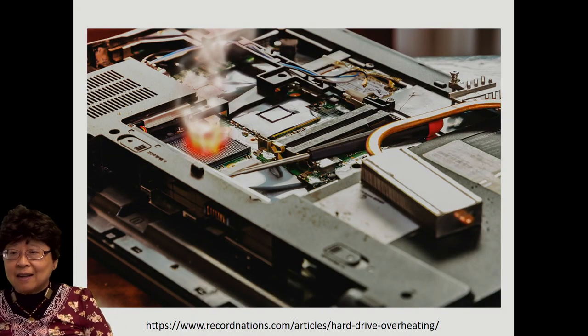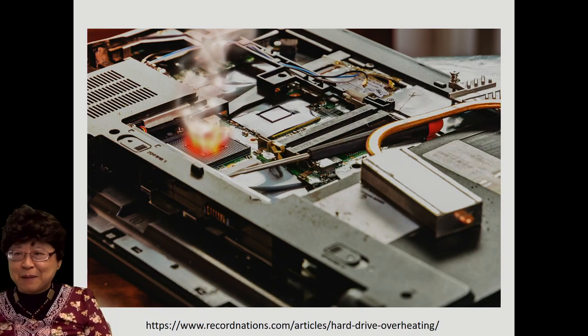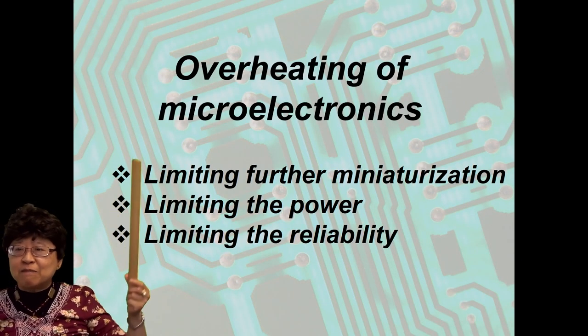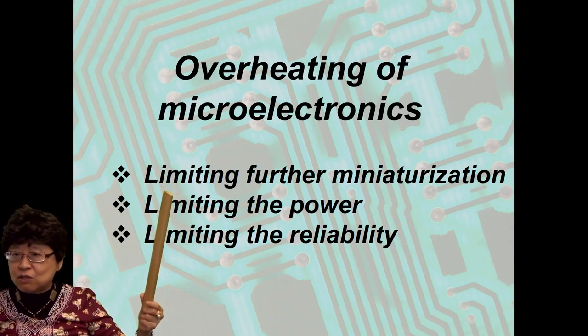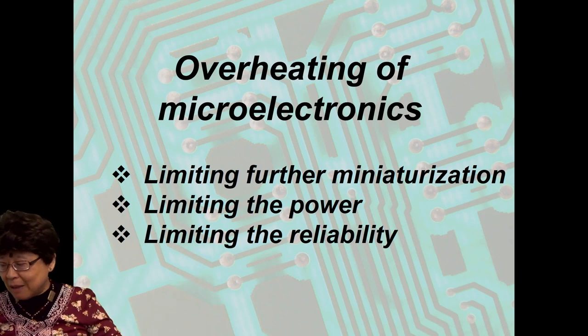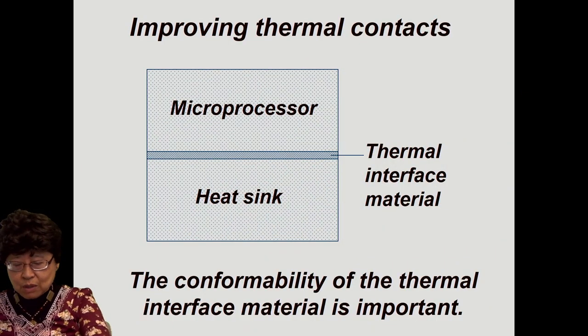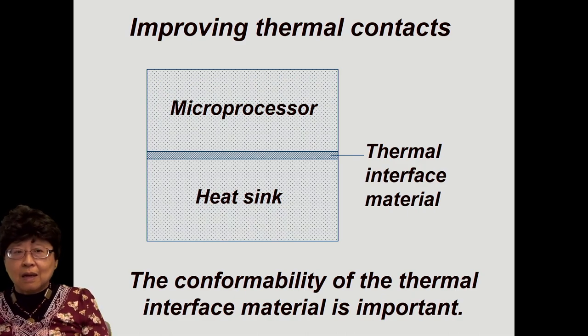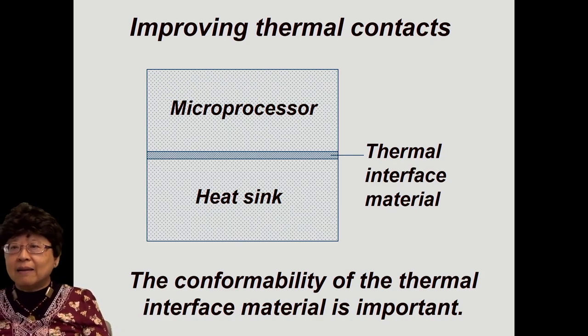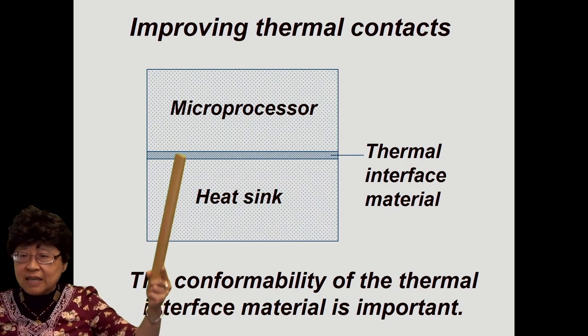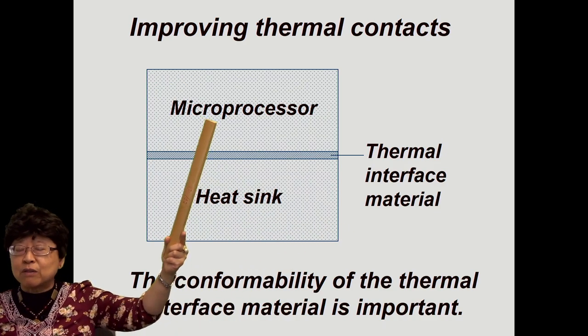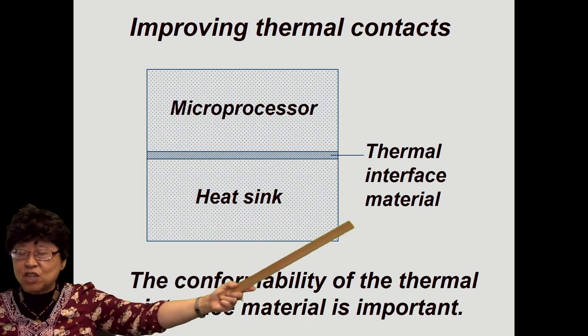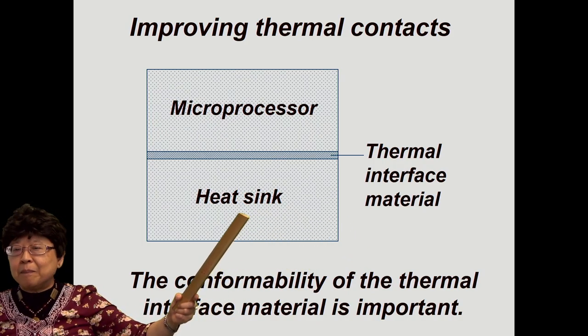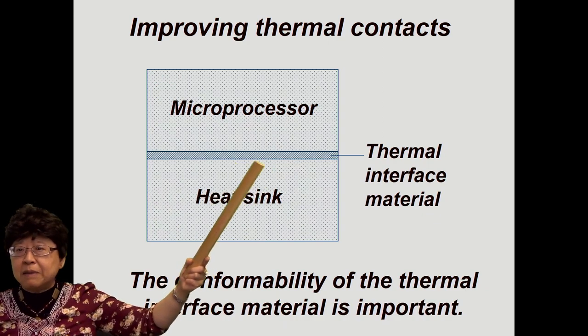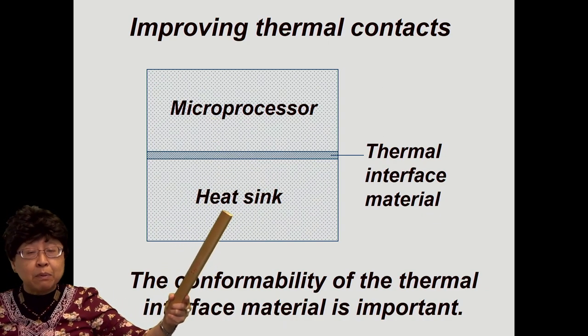Now, computers can get hot, and that is a big problem. The overheating of microelectronics limits the further miniaturization, limits the power, and limits the reliability. This is a big, big issue. To improve the cooling issue, and make it cool better, then we need a heat sink to channel the heat out. Okay, the heat coming from, say, the microprocessor. The heat goes to the heat sink and gets channeled out to the environment. But this thermal contact between the microprocessor and the heat sink is very important.